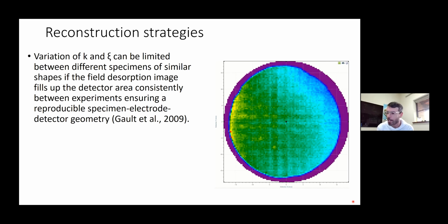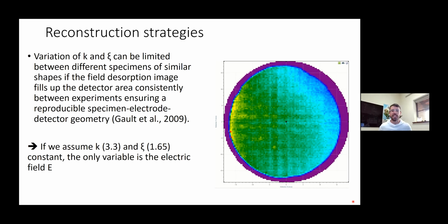And this will basically ensure a reproducible specimen to electrode to detector geometry. And I must thank him for this statement in one of his papers, because if we take care of matching the field desorption image consistently between our different specimens, then we can maybe assume constant K and Xi, which will mean that only the electric field will vary between different experiments, which then makes the equation much more achievable to resolve.